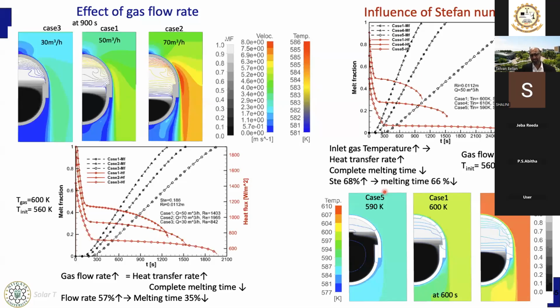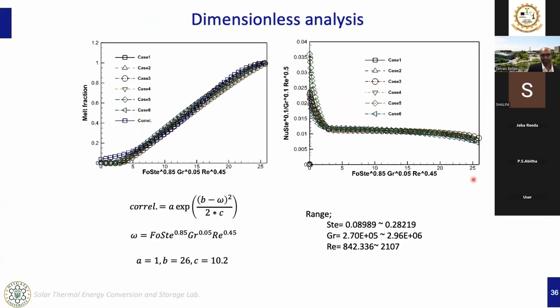Again, the profiles and the explanations are the same. Here you can notice that when we increase the Stefan number by around 68%, the complete melting time decreases by around 66%. Then we did the dimensionless analysis to obtain the generalized correlation for melt fraction and the Nusselt number. Using this Nusselt number, we can calculate the heat transfer rate between the capsule and heat transfer fluid for the thermal energy storage system.